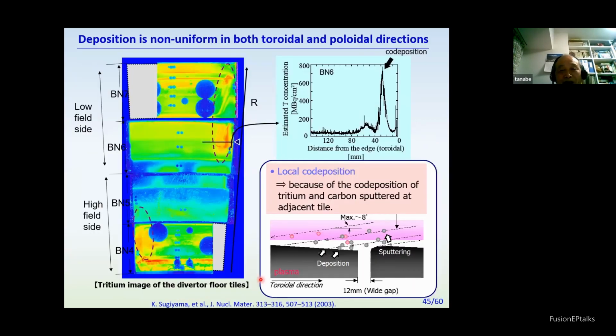Deposition on the plasma facing surfaces shows a difference in toroidal and poloidal directions. This difference is because there is a gap between the tiles - to avoid the edge effect, there is some gradient, and then there are gap differences. So these parts are eroded, and the eroded material is deposited here, including a lot of hydrogen. These neighboring tiles are eroded and then deposited, and this is opposite on the higher field side - this part is eroded and deposited.